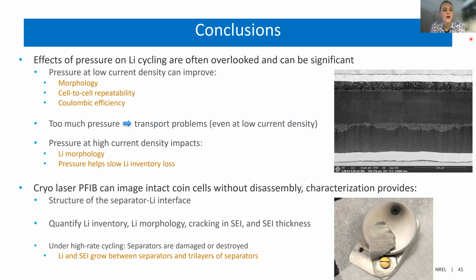The cryo femtosecond laser plasma FIB was able to image intact coin cell batteries without disassembly, and so that really helped us understand what those electrode thicknesses actually are, because you can imagine if you were pulling the separator off of the counter electrode or the working electrode, then a lot of that SEI might get pulled off with the separator, and so it's hard to do that characterization individually.